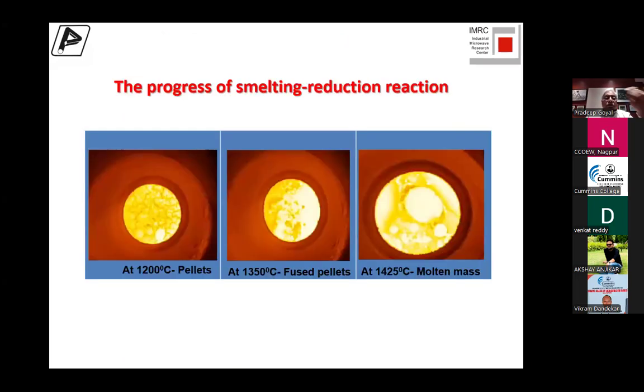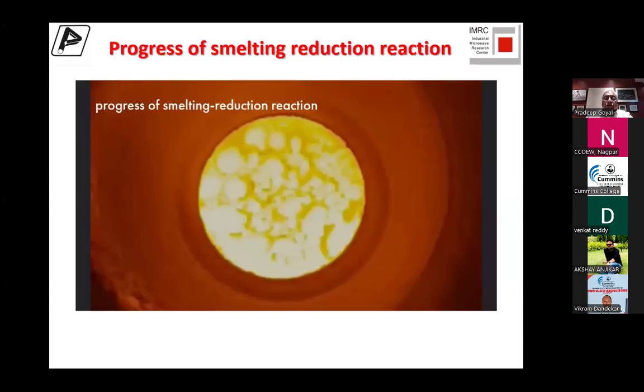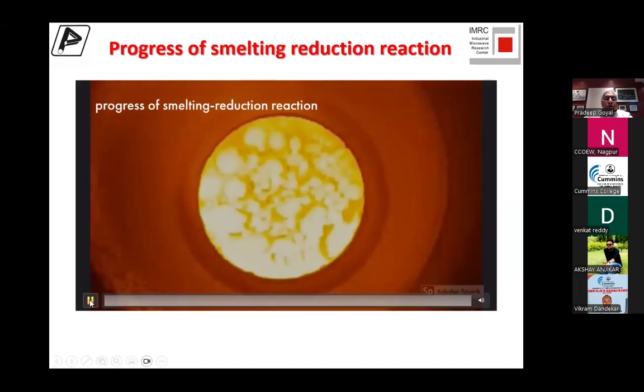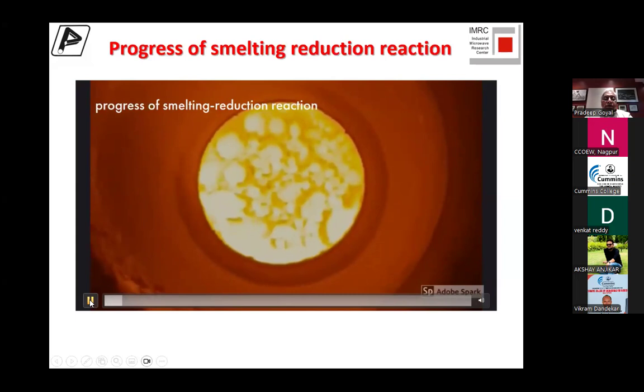So here I'll show you the progress, how the smelting reduction reaction takes place. We put pellets into this crucible. At 1200 degrees, you'll see some pellets. At 1350, you'll start seeing some fused pellets. And at 1425, you'll see a full molten mass. It was very interesting for us to go through this whole thing, which you can also see, how this process really occurred.